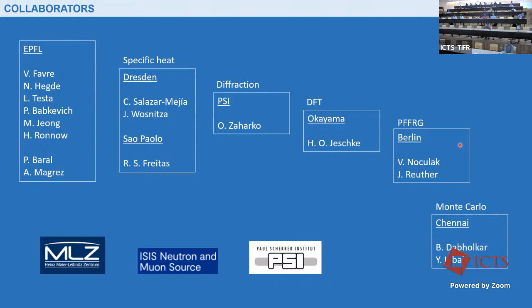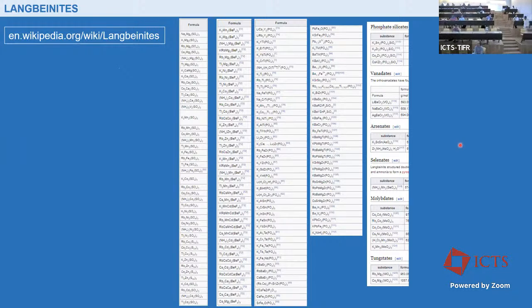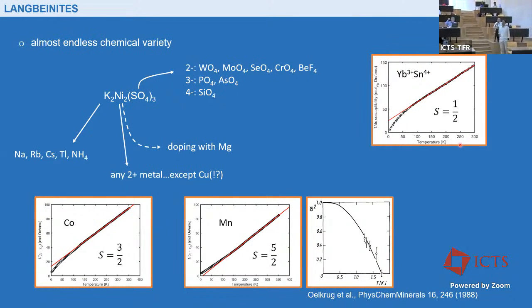Very nice talk. You have so many Mott insulators in this family. Is it possible to dope them and make them conducting, perhaps superconducting? Well, I would not dare to say no. On the other hand, the hopping integrals are rather weak, right? So your T over U is probably rather large. I don't know. I would try it if I were aiming at that and see what happens. I wouldn't hope too much, but I think one should try.